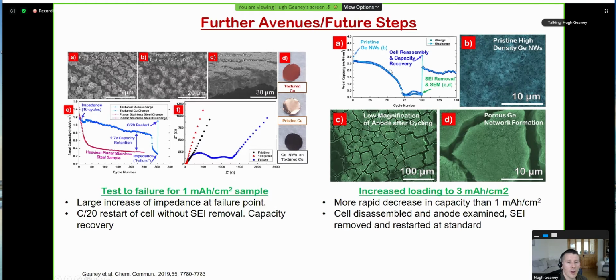But what we did find was that the capacity dropped off more rapidly than beforehand. So what I wanted to find out was, once we had reached this point here where you would think that the battery had failed, essentially, was to disassemble the battery and look at the active material. So what we found was that we had perfect retention of the material on the substrate, and we also had the porous germanium network formation. So essentially this issue here was not directly linked to the germanium.